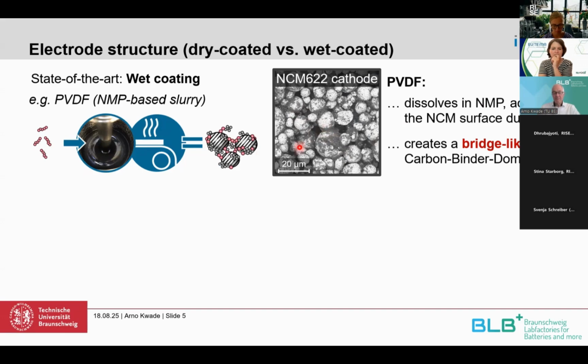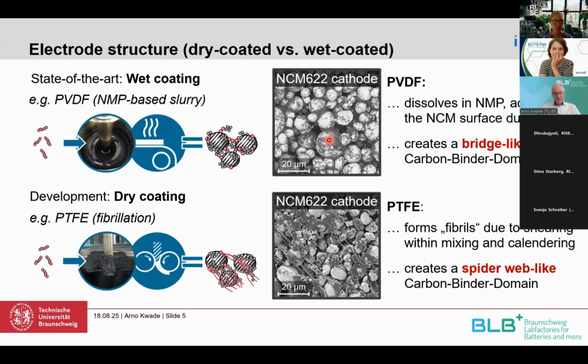And we use some NMP or something to dissolve the binder in the solvent. And in the dry coating or semi-dry is similar. We have, let's say, no or only a little bit of solvent, and we have usually binders which have a fibrillation like PTFE, which is in the moment really by far the best binder which we can use.